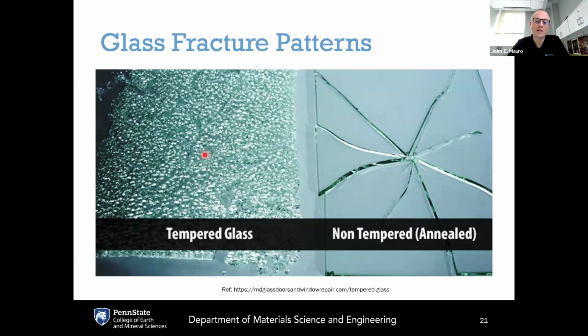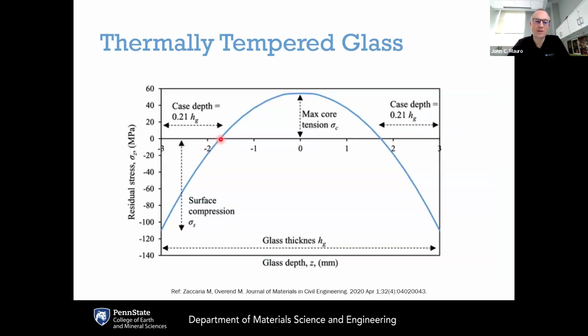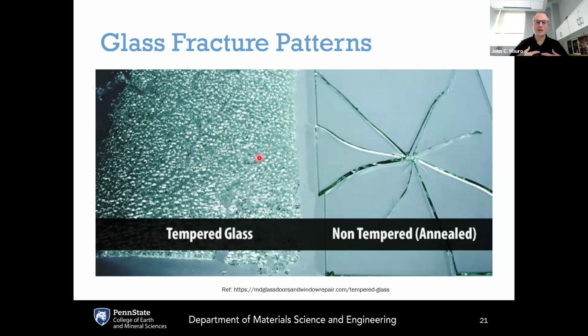With tempered glass, on the other hand, if the crack penetrates through this depth of layer and into this tensile regime, now the glass wants to release all of this tensile energy. The tensile energy release causes the crack to accelerate until it hits the terminal velocity, which is governed by the speed of sound in the glass. At that point, it still wants to release energy at a faster rate, but it's unable to travel any faster. So the way to do that is to bifurcate the crack. So one crack splits into two cracks.